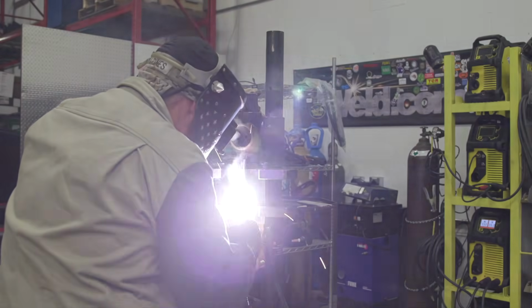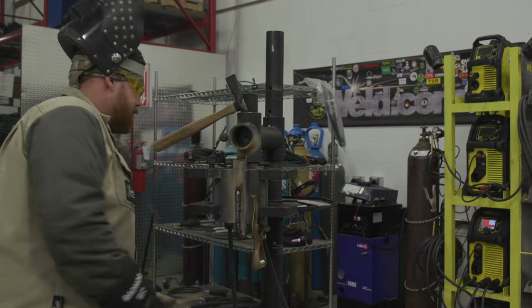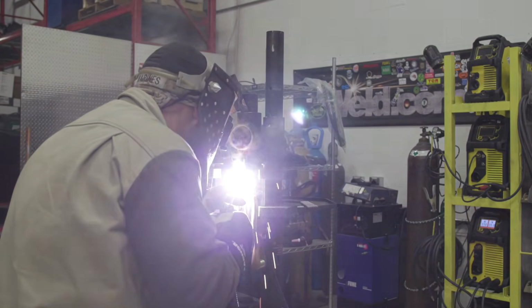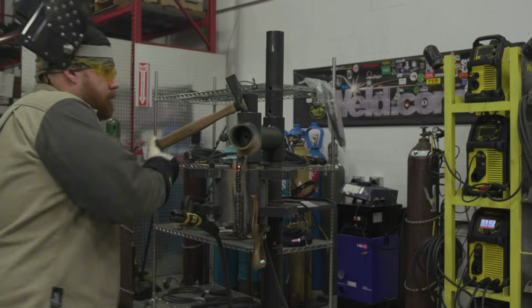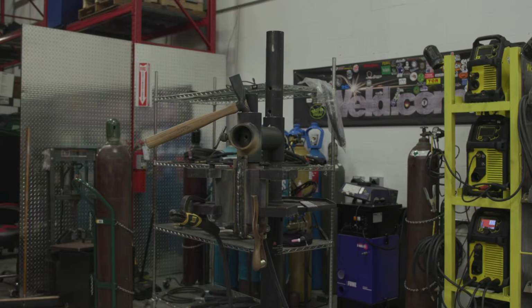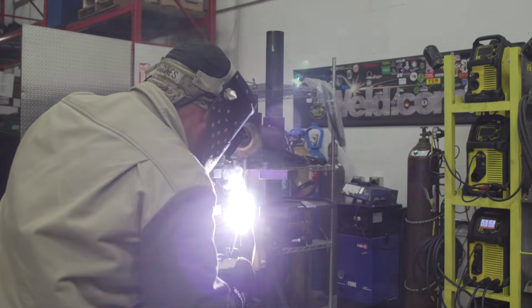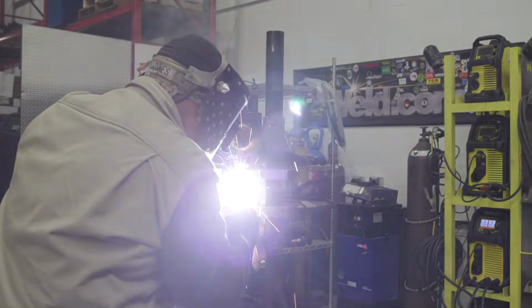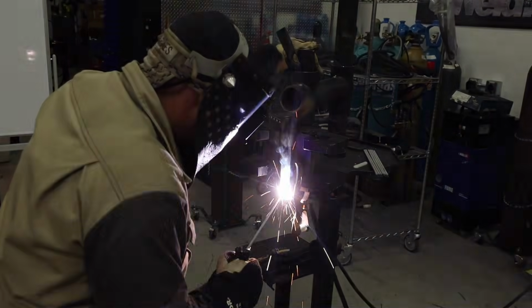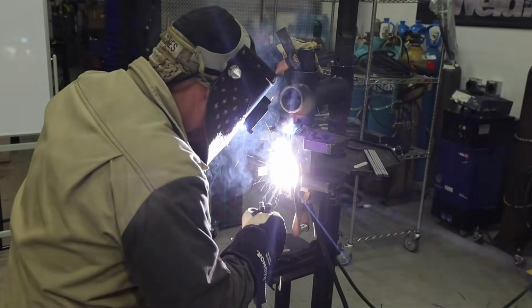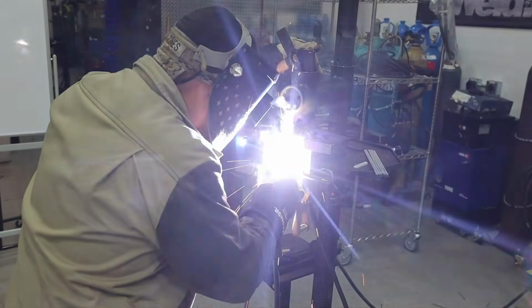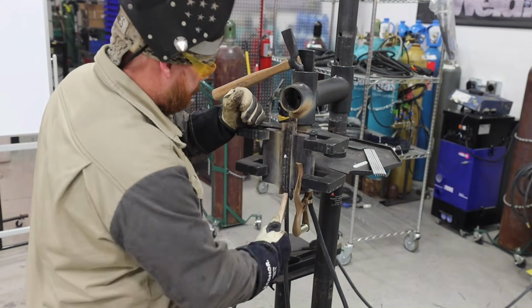Now when I'm throwing these passes in here, one thing that I'm gonna pay attention to is my interpass temperature. You can keep track of this with a Tempilstik. The crayon will actually, once it's 350 degrees or above, melt. This is personal preference again: when I get above 350 degrees and try to put my passes in, especially in vertical, that puddle becomes a little bit too fluid for my liking. It's harder to control, simply because the base metal is so hot.